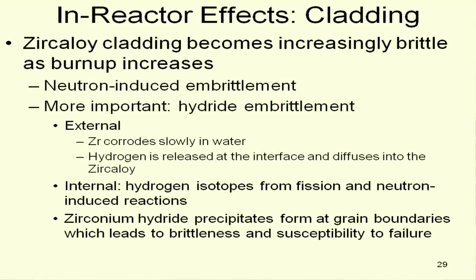You've got neutron-induced embrittlement just from dislocations, but for Zircaloy, the more important problem is hydrogen or hydride embrittlement. Zircaloy corrodes on the outside, corrodes very slowly in water, releasing hydrogen, which migrates into the Zircaloy and makes these hydride deposits, hydride precipitates, at grain boundaries, and that causes the brittleness. And internally there is hydrogen, there's a little bit of ternary fission stuff, there's some tritium in there, and all of that is sort of working from the inside. And of course, the more burnup you get, the more pronounced this effect becomes.